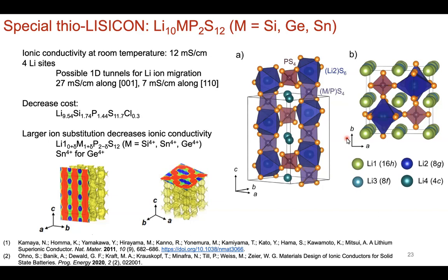But why does it have high ion conductivity? Is it the BCC sublattice of lithium? Is it the fact that there's a percolated network for these lithium ions to migrate at low energy pathways? All the answers, yes. So that's really exciting since 2011. So it's been more than a decade now. In terms of reducing the cost of germanium by incorporation of silicon and tin, there is mixed evidence out there as to the effectiveness of these substitutions for increasing ion conductivity.